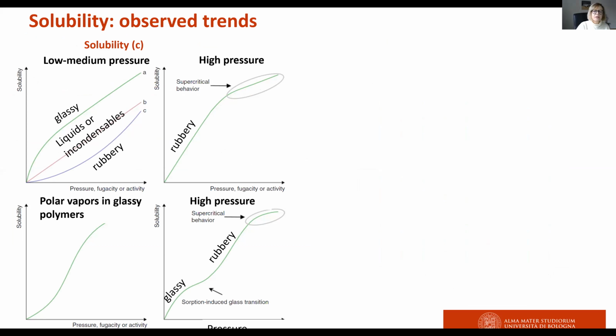Solubility is normally reported in the form of solubility isotherms. You can see different behaviors depending on whether the membrane is a glassy or a rubbery one. If you have an incondensable, a light gas such as nitrogen or hydrogen, you will see a linear Henry's law type of solubility isotherm. At high pressure, you can see strange behaviors like slope changes of the solubility isotherms due to the fact that the fluid becomes supercritical.